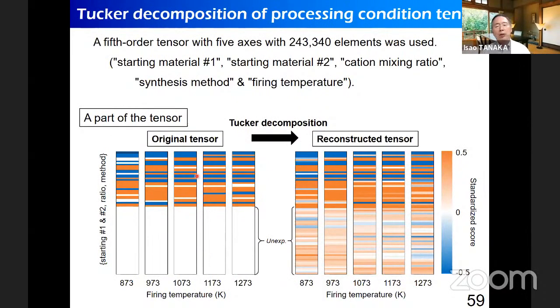This is a part of a 5th order tensor composed of 243,000 elements. The orange means a successful result, and blue means an unsuccessful result in the original tensor. This is just a cross-section of the 5th order tensor. And there is a wide range of unexperimented conditions. This is shown as white or blank. And after Tucker decomposition of this original tensor, we can obtain the reconstructed tensor, which can fill in these unexperimented conditions. You can find some unexperimented conditions show quite high predicted success, and the rest, the blue ones, are predicted to be unsuccessful.